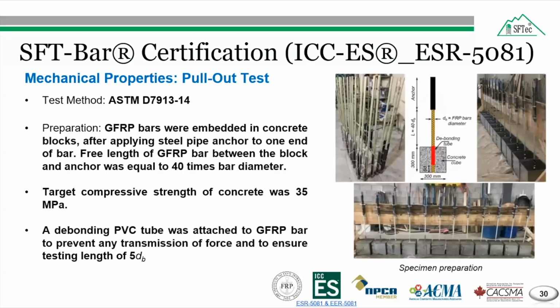The GFRP bar was embedded in the concrete blocks after applying the steel pipe anchor to one end of the bar as shown in this figure. And the free length of the GFRP bar between the block and the anchor was approximately equal to 40 times the diameter of the bar. And all the test specimens were prepared using one concrete batch, having a target compressive strength of 35 megapascal. A debonding PVC pipe was attached to the GFRP bar to prevent any transmission of the force by the bond between the bar and the concrete, to ensure a testing length of 5 times the diameter of the GFRP bar.